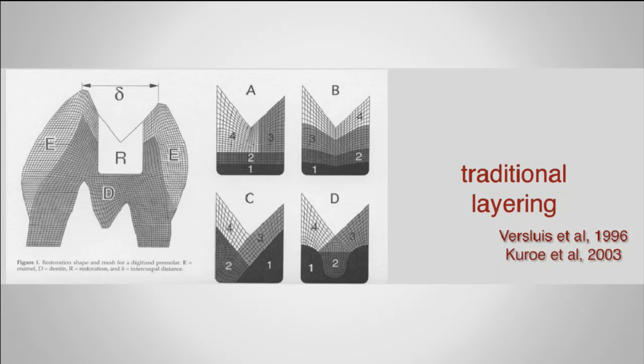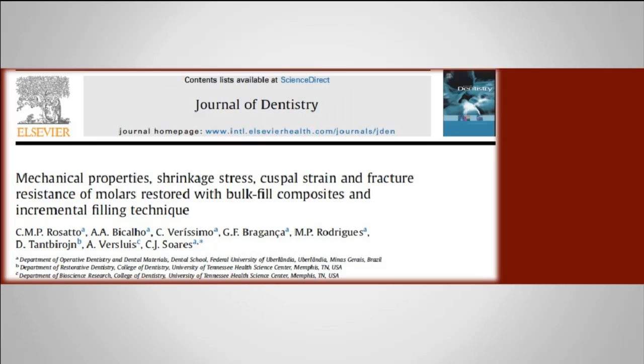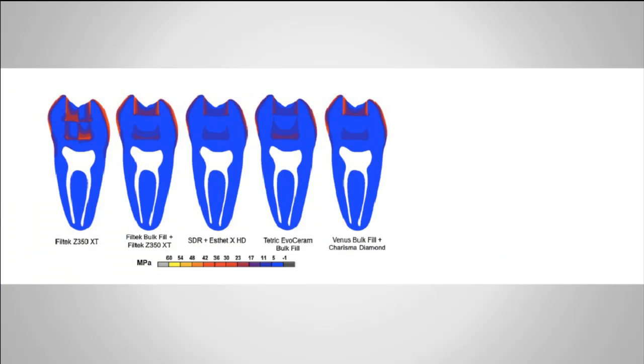For that, I think that you have to understand something about this bulk fill. The idea that I used to have about doing too many layers to control the interface, these old papers actually began to discuss the efficiency of using too many layers to control the shrinkage. It was not so true that I control so well doing too many layers. These are old papers, but I have a newer one. This is done by a friend of ours from Brazil. But if you check this paper, it's something interesting.